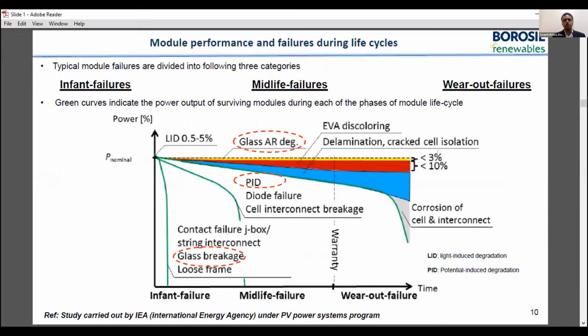That's how solar glass is important, and why we should be careful while selecting solar glass is this very popular graph that almost everybody refers to. The failures are categorized in three categories: infant, midlife and wear out failures. Infant failures happen very quickly, and those related to glass are primarily glass breakages. In midlife failures, potential induced degradation is one of the major causes. Over a period of time, other issues like snail trails or degradation of anti-reflective coating cause underperformance of the solar module, which are directly related to solar glass.